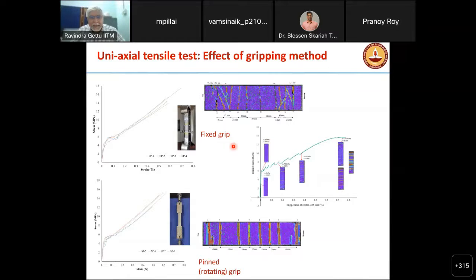We are looking at different ways of testing because we have to understand how to test it. So even the end conditions matter, as is shown here. So we have the panel with a fixed grip where we are fixing both the ends and then pulling, or we are rotating. We are allowing for rotation. That is what we call a pin grip or a rotating grip. What we have found is, after a lot of research, we are able to get both of them systematically, but there are some changes. For example, in the fixed grip, what happens is as you pull, the specimen has to accommodate the change in the load direction.